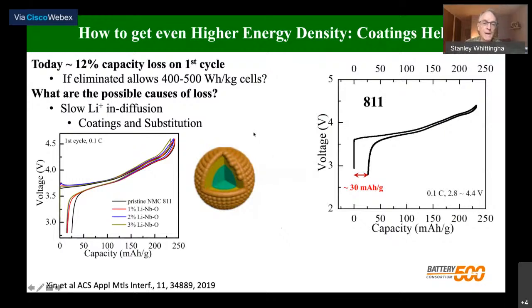So one of my postdocs is now looking at coating this material, and what she's using is a lithium niobium oxide. So we take the commercial NMC particles like this one, soak them in a solution of lithium niobium oxide, and then fire that solution at about 400 degrees centigrade. And then you get this brown coating as I show here, and it diffuses a little bit into the particle, just a few nanometers. And you can see the effect of this.